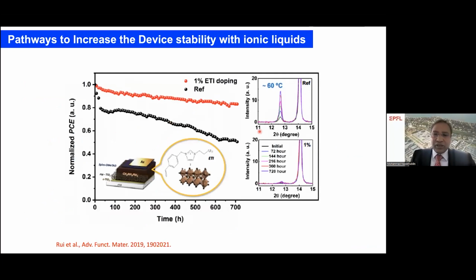Stability data is shown here. The XRD data is very clearly demonstrated here at 60 degrees temperature. As time goes on, you can see the formation of lead iodide increasing from 0 hours to 720 hours. You can see the presence of lead iodide. This is an indication of decomposition of the perovskite material. However, if you have only 1% of this ionic liquid in the composition, even after 720 hours, you can see very small formation of lead iodide, but otherwise it's showing extremely stable performance.